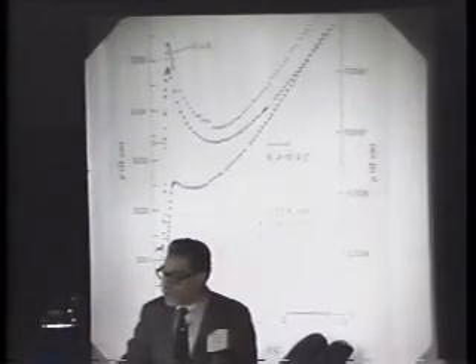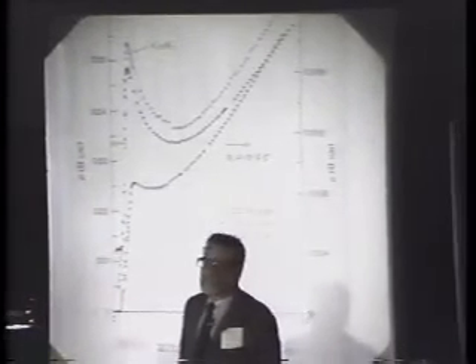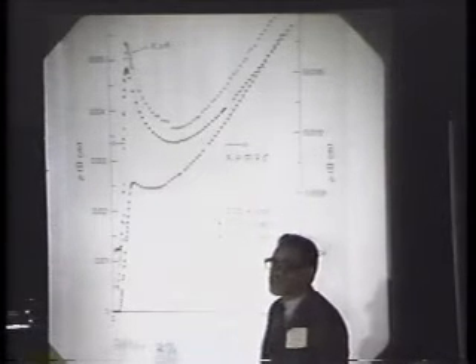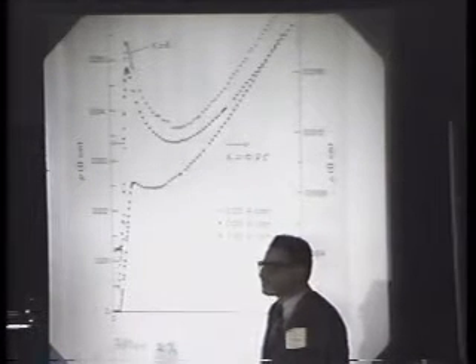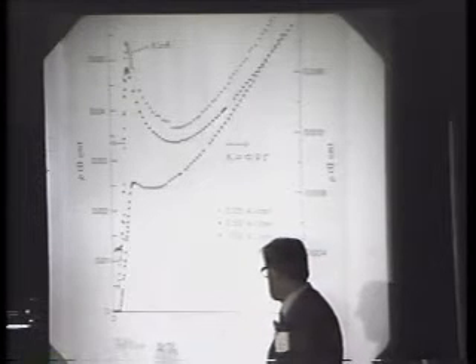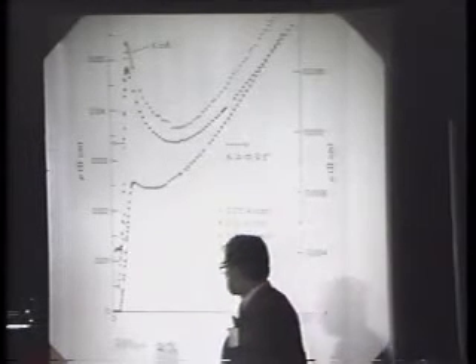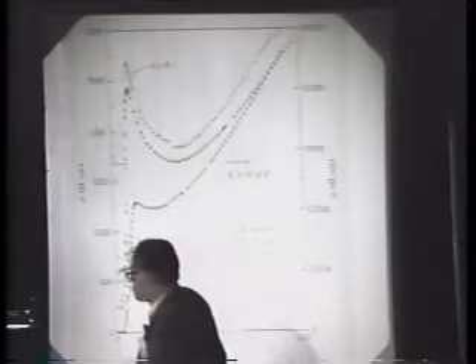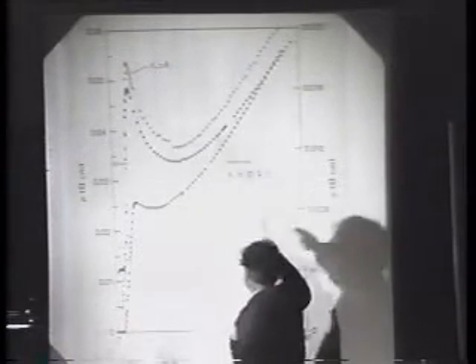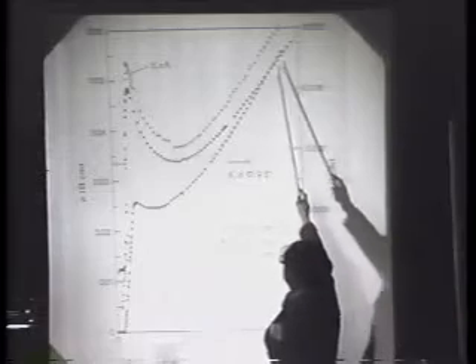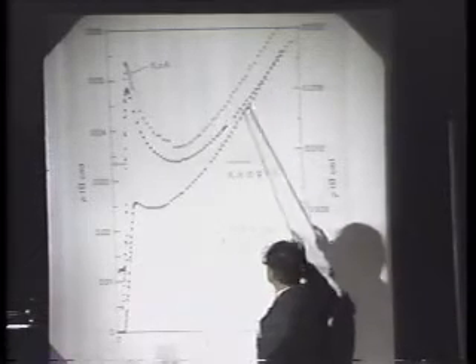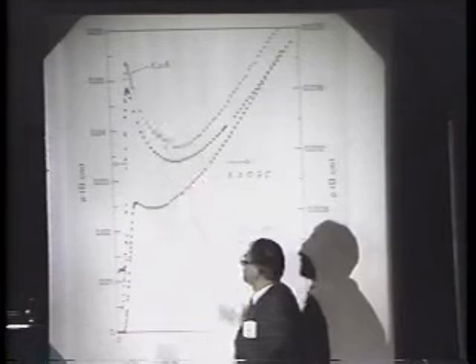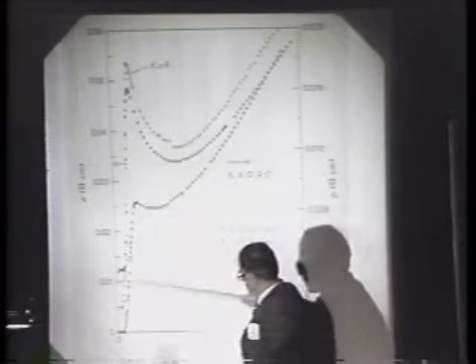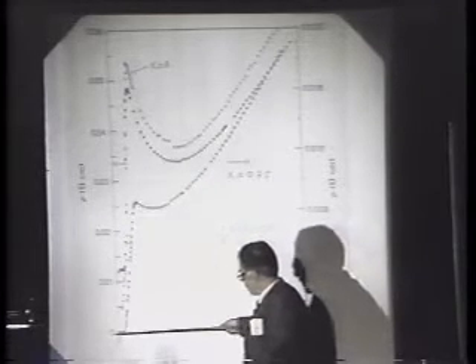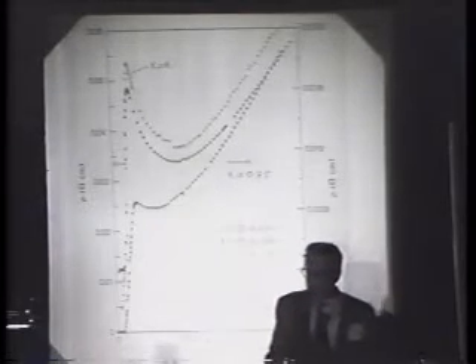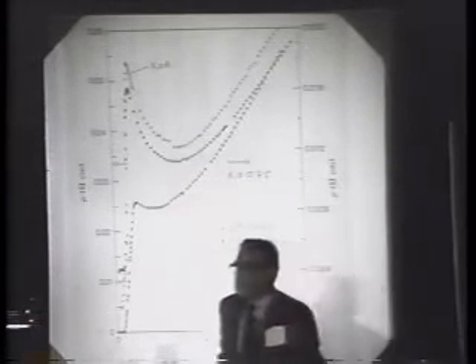Essentially, the whole search extended over about 2.5 years. It was strictly a two-man project. Not even a technician was involved. It was George Bednorz and myself. And you see here that the resistivity as a function of temperature decreases metal-like, and then has a tendency to localize, and certainly you get the onset. For example, for this sample, we couldn't measure, at least with our equipment, any resistivity anymore.